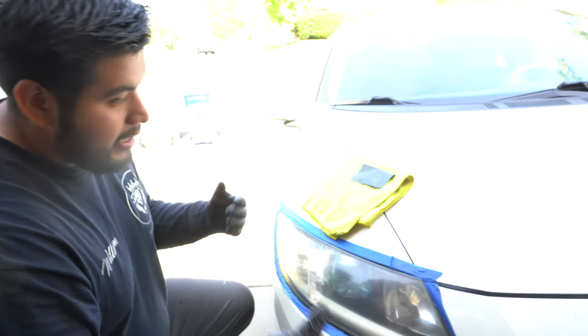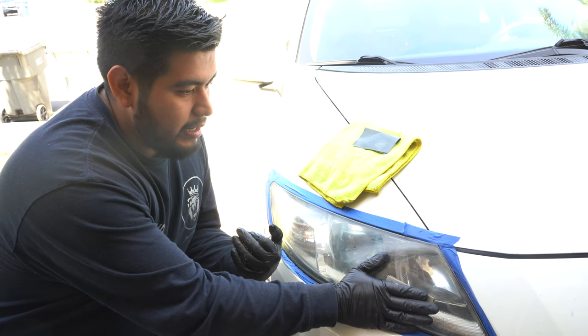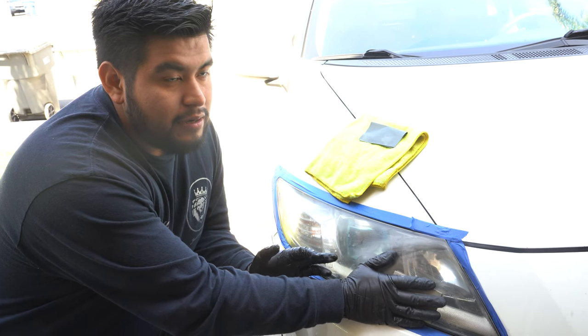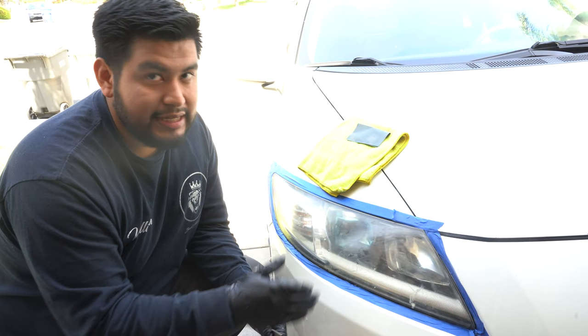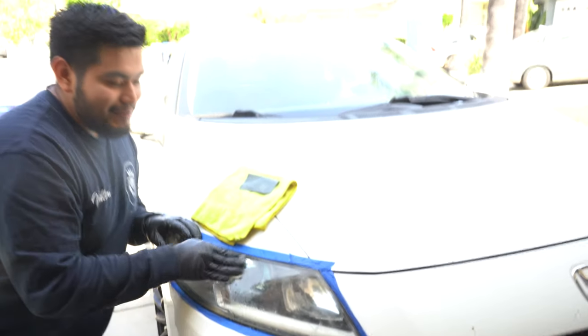You can see the fog on the headlight and where he's worked it's already looking ten times better. He finished the 2500 grit pass, now going with 3000 to refine and polish a little bit, then the compound to restore the headlight. When he finishes detailing the whole car, he's adding ceramic coating on the headlights as a package. Without protection, the sun will still eat the headlight back up - but with ceramic coating it will take two to three years to re-oxidize instead of two to three months.